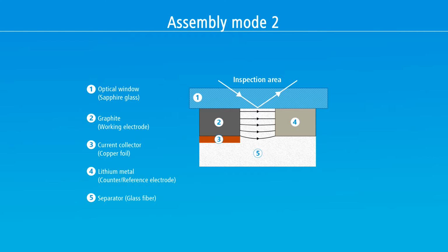This video is to explain another assembly mode of the ECC-Opto standard test cell, referred to as mode number 2 in the manual. In this example, a 1 mm wide electrode strip cut from a conventional graphite electrode with copper foil current collector is being used as a working electrode. This electrode strip is placed beside a lithium metal foil connected to both the counter and the reference electrode of